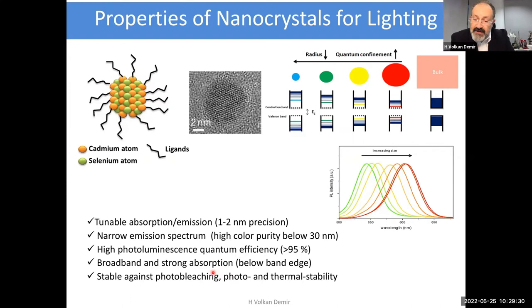At the end of the day, being semiconductors, I think one benefit comes inherently, and that is as long as you are below the absorption band edge, you have the ability to pump these materials. So broadband and strong absorption is surely a forte compared to phosphors, because phosphors, including rare earth elements, they have only very limited absorption band. And even if you get the emission wavelength right, 90% of the time, you will not have the absorption band right. So most of these type of very promising phosphor materials are screened out because of the mismatch for the absorption. Finally, photobleaching, photo and thermal stability issues are well addressed with right configuration of such emitters, where instead of having only single core, you can actually have multi-shelled structures, and you can introduce additional barrier materials.